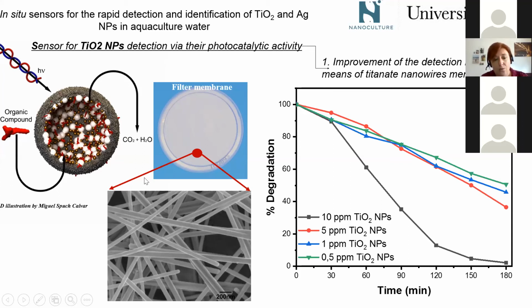So we are using this property in order to track the presence of the titanium dioxide nanoparticles in the water. What we are doing is to use supports in order to have filters for concentrating the nanoparticles that are present in the water. And then we expose these filters with the titanium dioxide nanoparticles trapped to a dye. This dye, in the presence of UV radiation, will get destroyed or degraded on the concentration of titanium dioxide nanoparticles that we will get. And as you can see here in the first, in the initial assays, we got a sensitivity around 10 ppms.